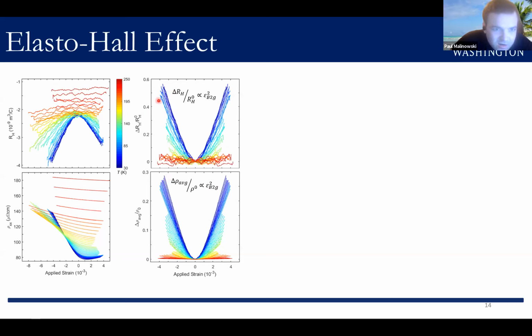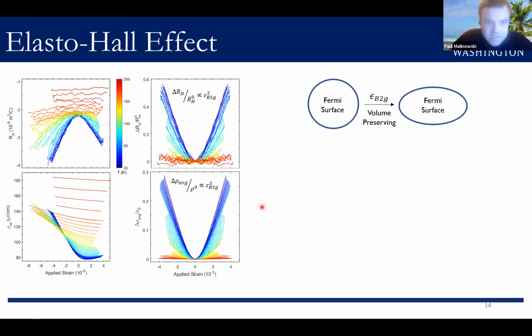And notably, the Hall coefficient is actually even more sensitive than the resistivity, if you look at the numbers here. So at first sight, this is quite surprising because the zeroth-order interpretation of the Hall coefficient is that it's a measure of the carrier density, or equivalently, the Fermi surface volume of the system. And since anisotropic strain is a volume-preserving distortion, although we expect it to change the shape of the Fermi surface, we don't expect it to change its volume, and thus don't expect it to change RH.